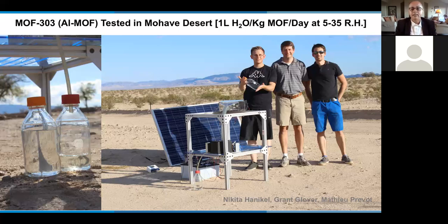The MOF, in this case, so far has been tested over 30,000 cycles and still performs perfectly. You'll see why in a second. And it can stay in the device for 5 to 6 years. That's what it's graded for. So then basically you have a scenario where the MOF is working day after day and month after month, year after year, all because of the strong bonds that are holding the structure together.